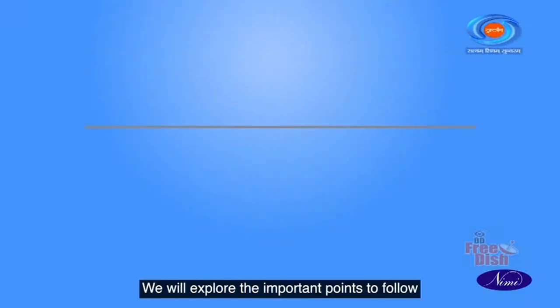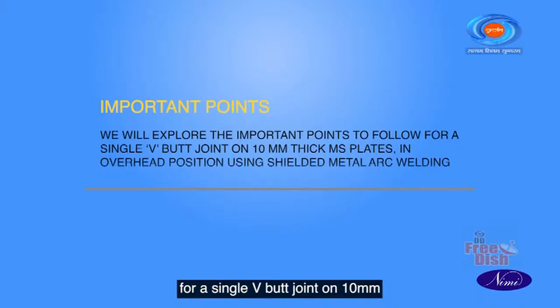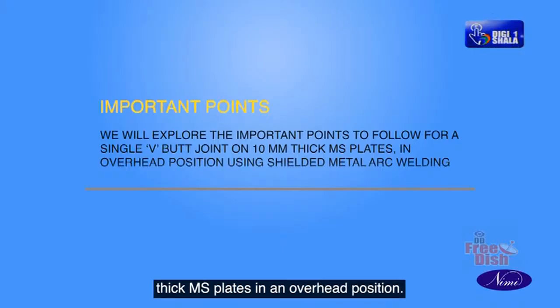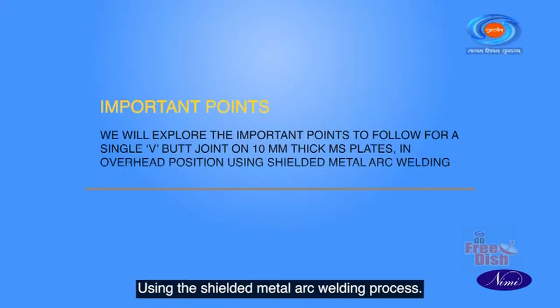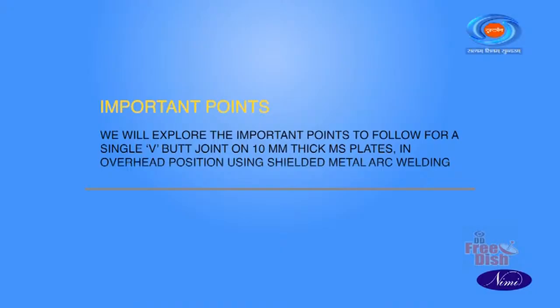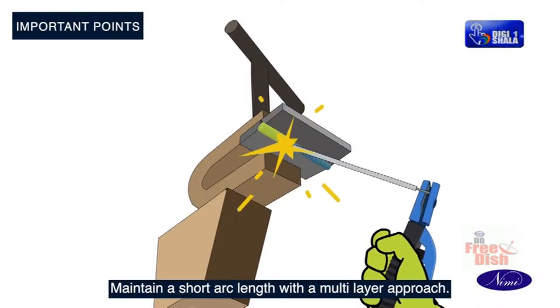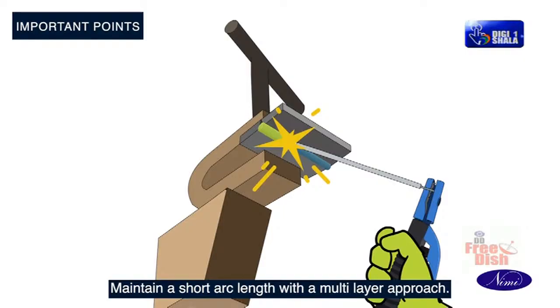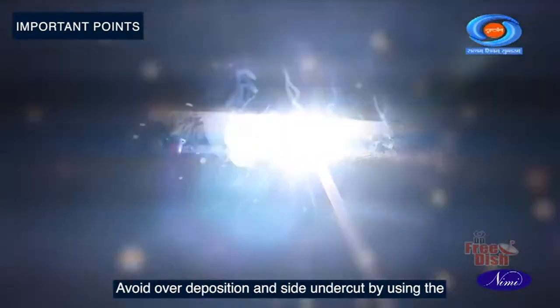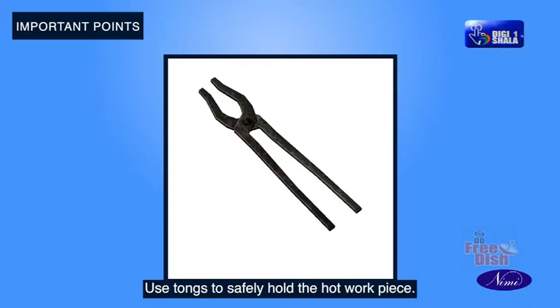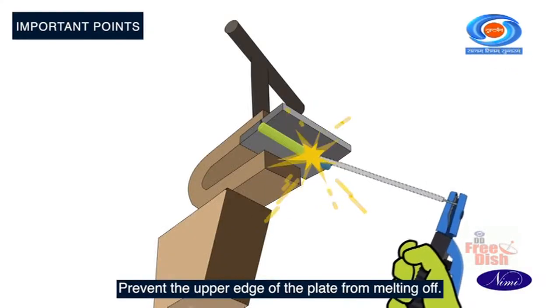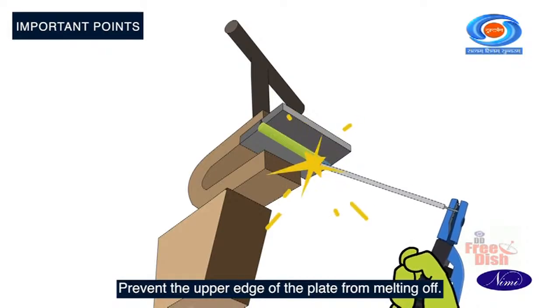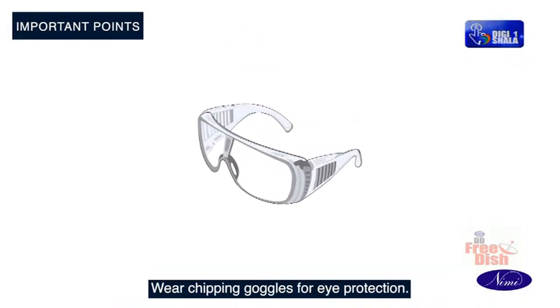We will explore the important points to follow for a single V-butt joint on 10 mm thick MS plates in an overhead position using the shielded metal arc welding process. Maintain a short arc length with a multi-layer approach. Avoid over-deposition and side undercut by using the proper angle and travel speed of the electrode. Use tongs to safely hold the hot workpiece. Prevent the upper edge of the plate from melting off. Wear chipping goggles for eye protection.